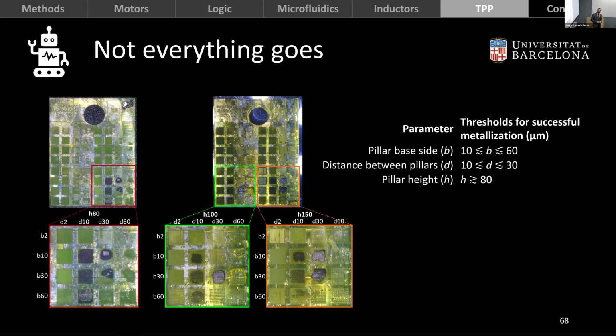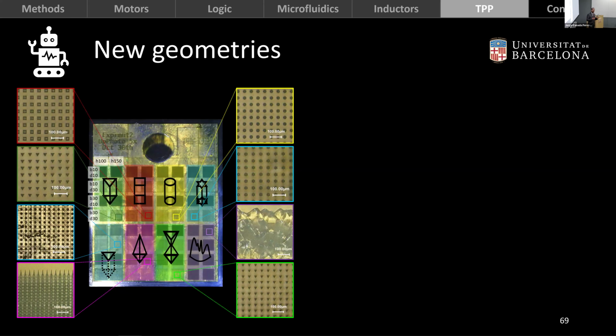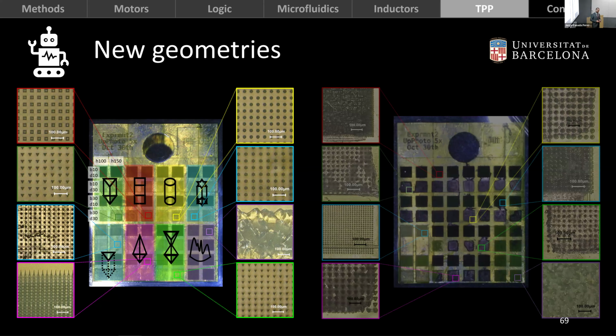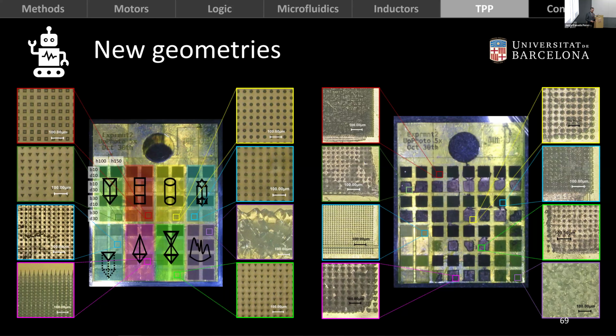And we also tried different geometries. So not only triangular prisms, but also square ones, cylinders, star-shaped, triangular holes, pyramids, sand clock structures, and even randomly generated peaks and valleys. And what we saw from this is that, again, not everything works, but many do. The surprise was basically that the holes do not work, and the randomly generated patterns also do not work. But all other textures that were defined basically by a flat surface with high aspect ratio structures coming out of it, those do work.